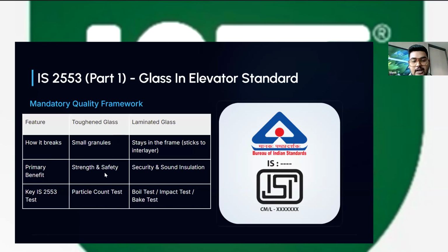So if we talk about the standard, the first thing that comes to mind is the particle count test. This is a must-have test for a toughened glass, which states that when a toughened glass breaks, the particles, the pieces which are formed, should be within the minimum quantity that the government has stated, and we need to follow it. If the particles are less than the given standard or more than the upper limit, then the glass is not properly toughened, or it's toughened too fast, which is not good.